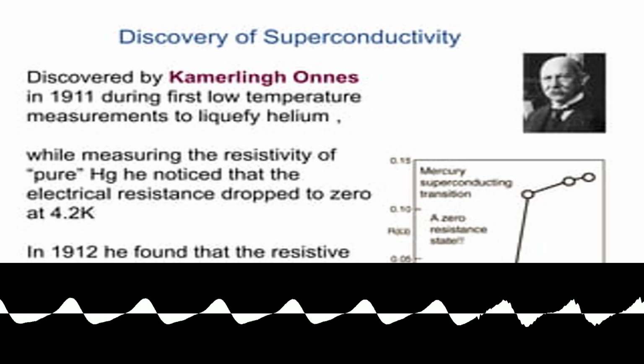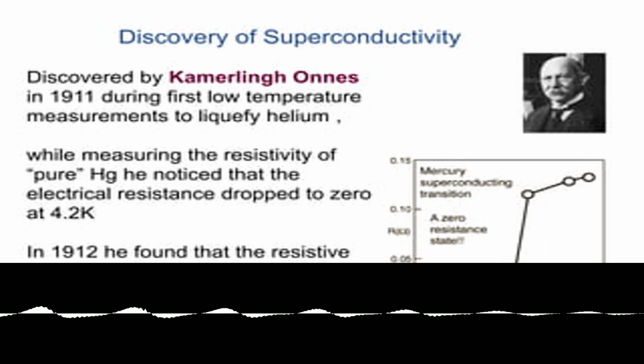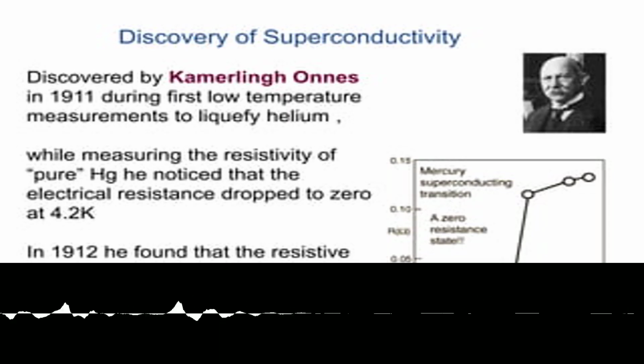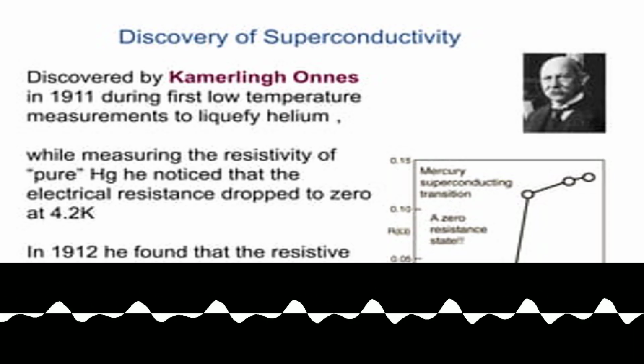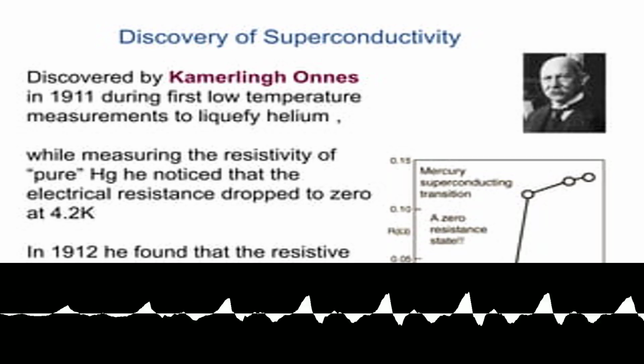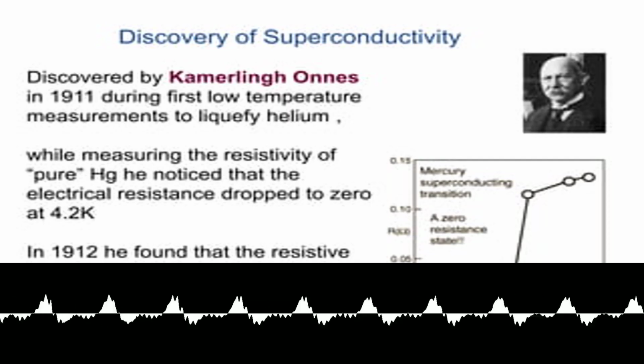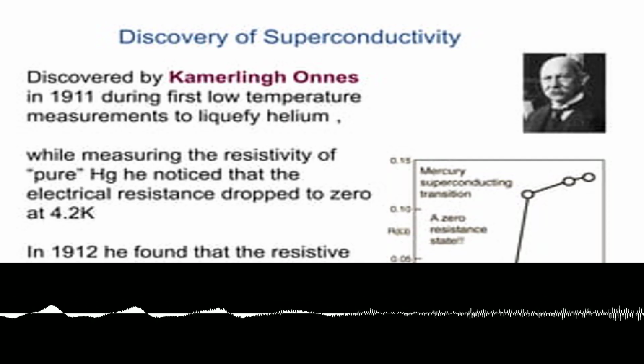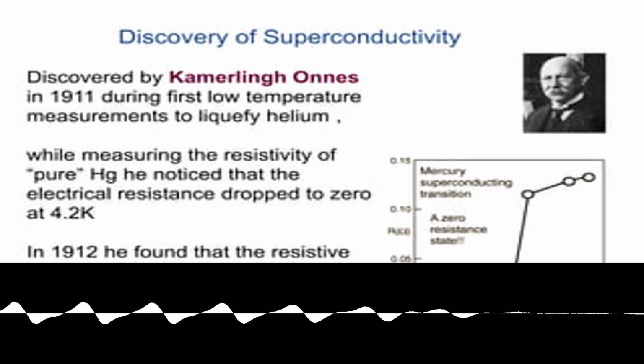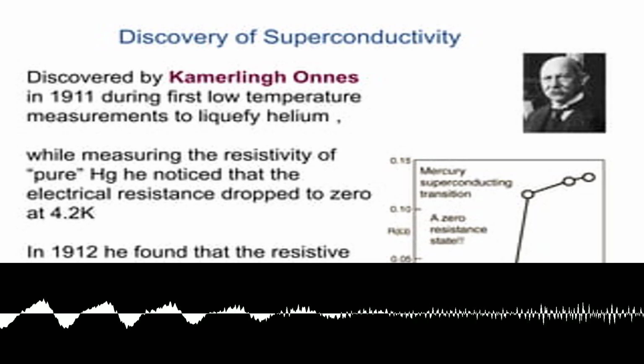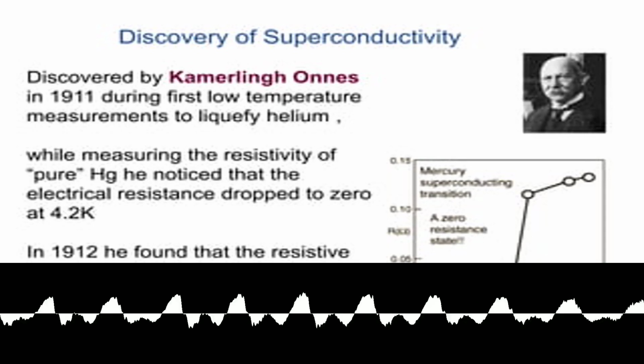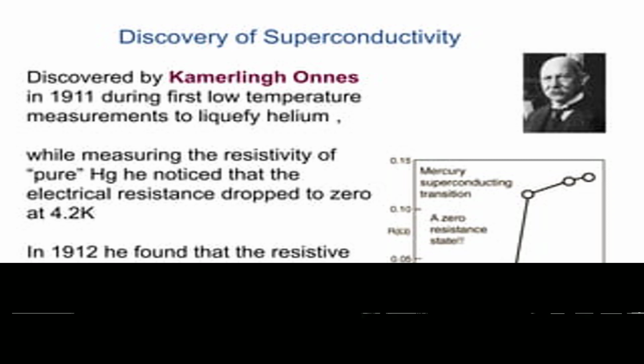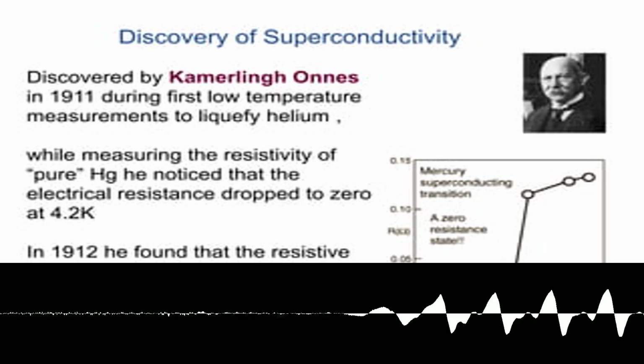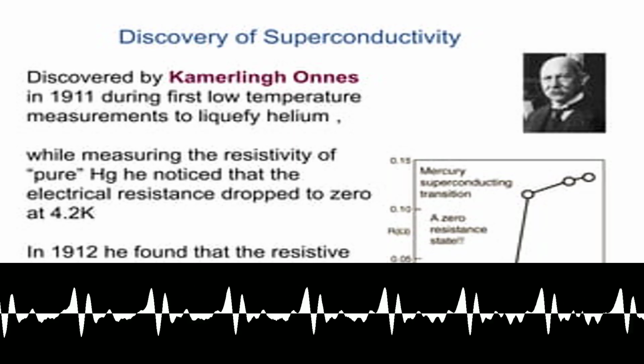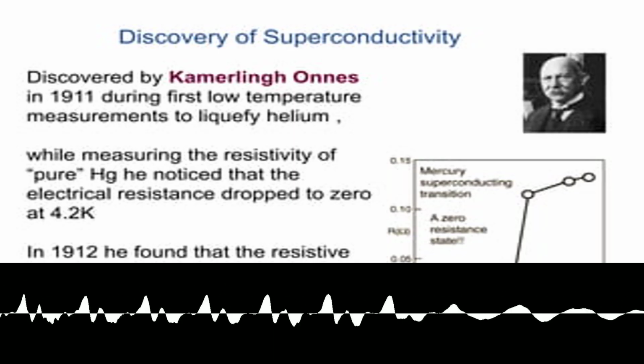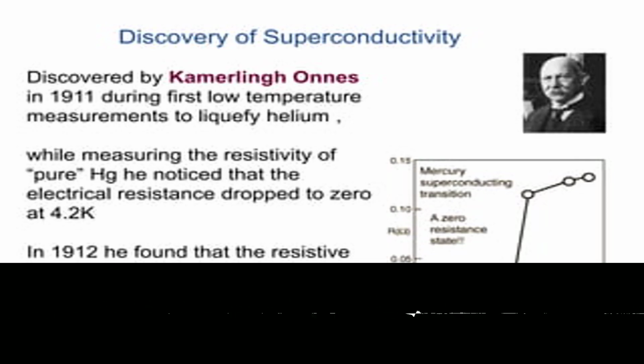Section 2. The initial anomaly in the resistivity of mercury. The pivotal discovery, as detailed in reports from 1911 and consolidated in the later understanding, centered on the electrical resistance of a thread of exceptionally pure mercury. The central claim here is twofold: that the resistance dropped precipitously and that it fell to a value experimentally indistinguishable from zero. The initial hypothesis, rooted in classical physics and Lord Kelvin's conjectures, was that the resistance of a pure metal would fall to a low, constant value as thermal vibrations of the crystal lattice ceased near absolute zero. His experimental data directly contradicted this.